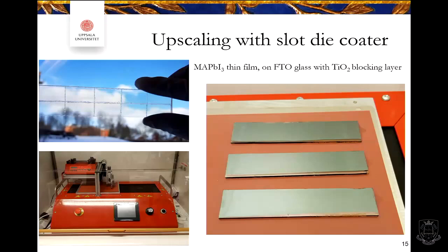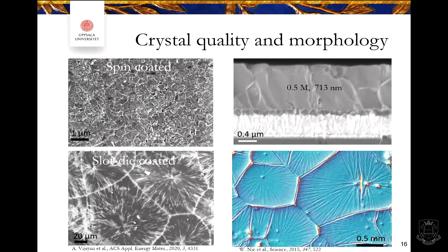But this is an example of perovskite, the simplest one, on FTO glass, fluorine-doped tin oxide glass, and TiO2 blocking layer in this case. So it works too, but there are differences which don't necessarily have to be bad, but they look very different if you look, for instance, in scanning electron microscopy. So these are SEM images of the surface. Here you have the spin coated. This is usually what you see when you look at the spin coated film. Small grains, or comparably small. Also observe the scale bar here and the difference in scale bar.